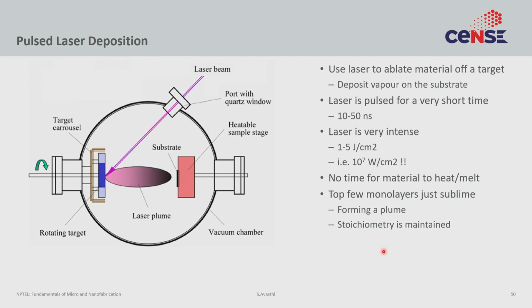Last slide on a related cousin to sputtering, which is pulsed laser deposition. In a lot of ways, pulsed laser deposition is a cross between evaporation and sputtering. It has advantages of both. So the basic idea is that here the energy is being provided by a laser beam. The laser beam is pulsed, hence the pulsed laser deposition. And this is a very high power laser. So it falls on a target and it is absorbed in the first few nanometers. And the energy is so high that the first few nanometers instantly sublime or ablate. And they don't just ablate, but their electrons are stripped away, so they ionize.